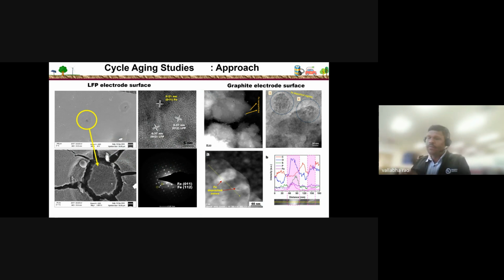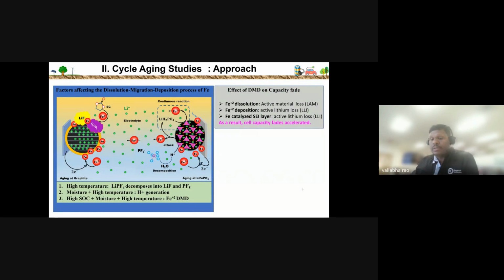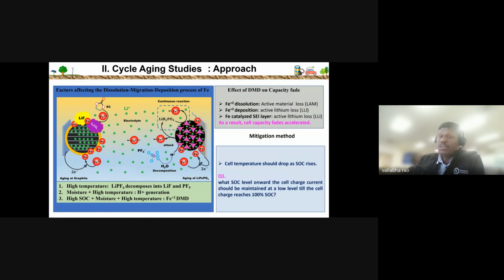So this is the effect we have identified, and this effect is due to the cell temperature rise. If we can reduce the cell temperature rise over the cycles, then we can mitigate this aging effect. That's our understanding.